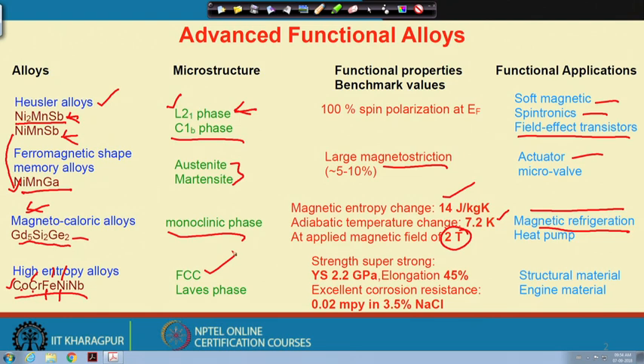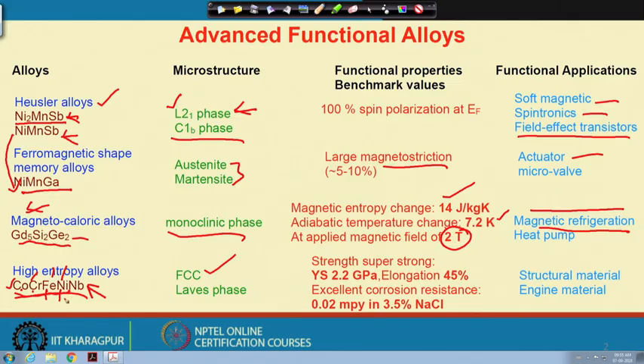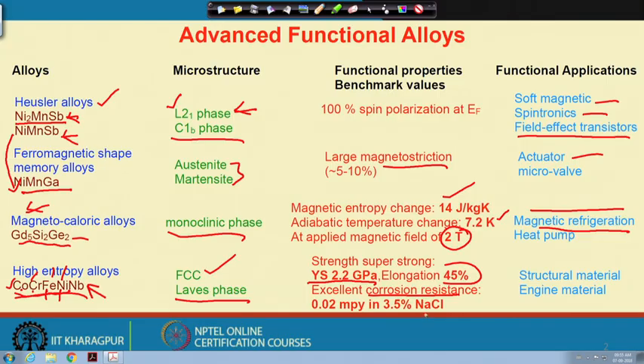And that may have some strength level of 800 or below 1000, which can be further processed to make a very nanocrystalline microstructure, or maybe by adding some niobium into this alloy with these 4 principal elements, we can incorporate some Laves phase, or Laves phase may form due to the addition of niobium, and the yield strength can reach up to 2.2 gigapascal. So, this strength level is almost reaching close to the theoretical strength like metallic glasses, and we can also achieve very high elongation, very high corrosion resistance in an aqueous medium, let us say